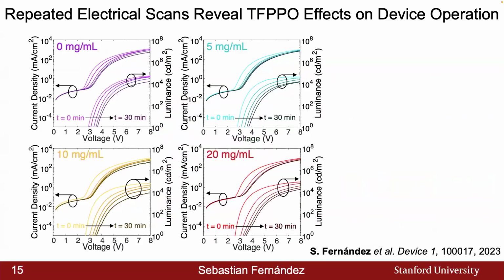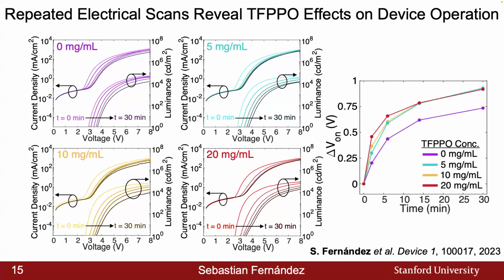So the first one I'd like to focus on is the evolution of the turn-on voltage, which is defined as the voltage when the device reaches a luminance of 1 candela per meter squared. And what we can see here generally is that the devices that have TFPPO have a much stronger degradation in the turn-on voltage, which implies that the injected carriers in the device see a much harsher obstacle to recombination that leads to light emission within the device itself.